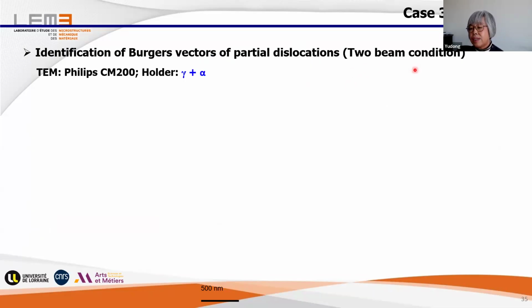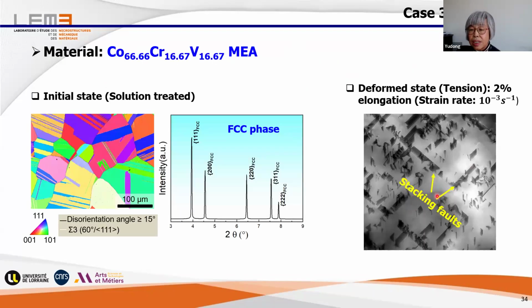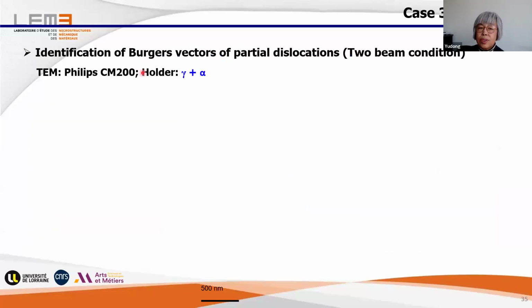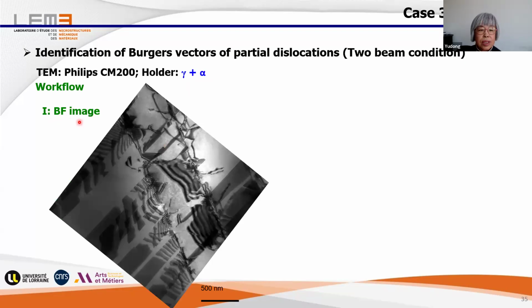Then we need the two beam condition. We used our TEM. It's a very old TEM, nearly 30 years old. But you see the contrast is wonderful. And then we use a gamma plus alpha holder. And then the workflow is like this. We put the sample into the TEM, and then heat the filament, and then take a bright field image at 0 tilt position. And then we see the image is here, and then we see twin boundaries.